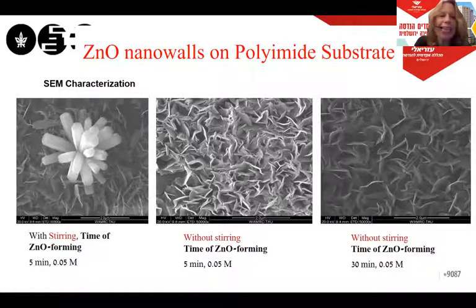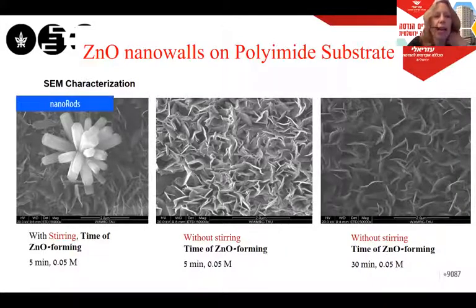When we did exactly the same details, the same concentration, the same temperature, the same time, we got some nanorods when we did it with stirring and none when we did it without stirring. And it didn't matter how long, if it's 5 minutes or 30 minutes, but still we got better results without stirring. So that was our first conclusion, that without stirring is a better way to deposit on polyimide at least. So we don't want to get nanorods because the surface area is smaller.